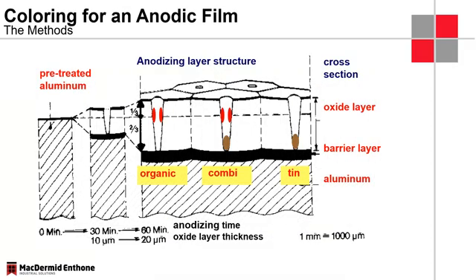So we see that here again, organic colors here in the top third of the pores. Then we have combinations where we have an electrolytic color combined with an organic color to get even deeper shades of black mainly. And then here right on the right hand side, we just have that tin coloring solution that deposits the tin and the color at the bottom of the pore.